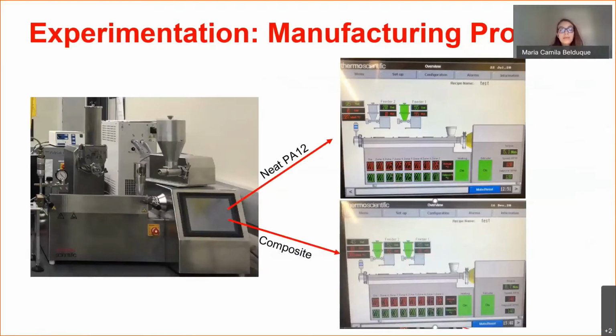Here we can see the parameters used in the twin screw extruder to manufacture both the neat PA12 and the composite. This machine has two volumetric feeders. For neat PA12, we only use the main one, which has one screw. The temperature, feed rate, and screw speed vary according to the material. In this case, we decided to increase the temperature a little bit above the melting point of the PA12 and also apply vacuum. And for the composite, we have to use both feeders.